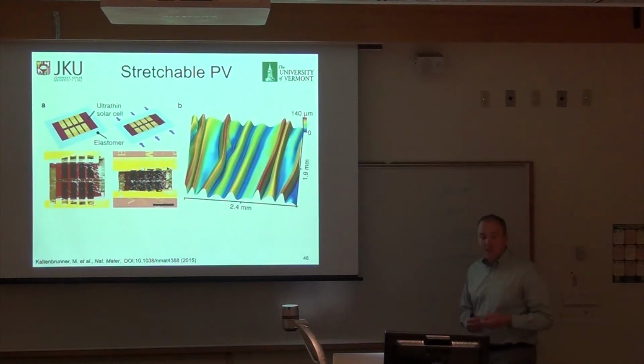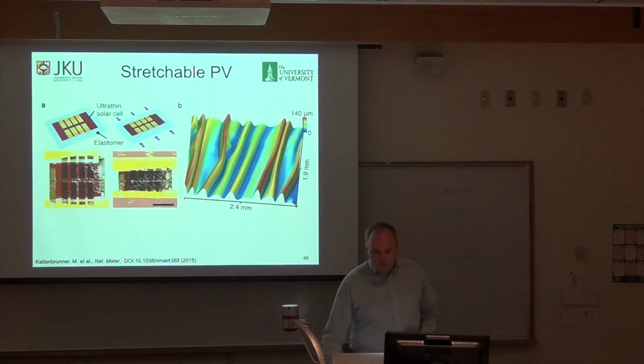They're thin enough that if you take an elastomer like a rubber band, stretch it, you can glue the film to the top, and relax it, and it will form a network of wrinkles and folds to conform to the elastomer without damaging the devices themselves. These wrinkles and folds sometimes have radius of curvature down to 5 or 10 microns - very small wrinkles, very small folds, but almost no damage to the devices.